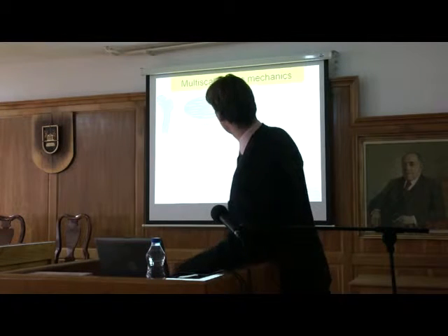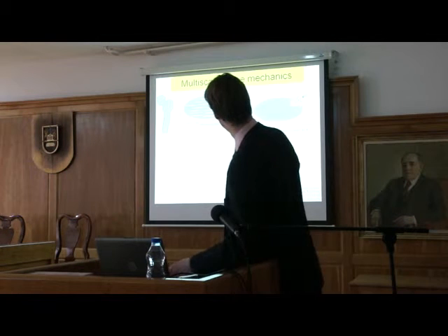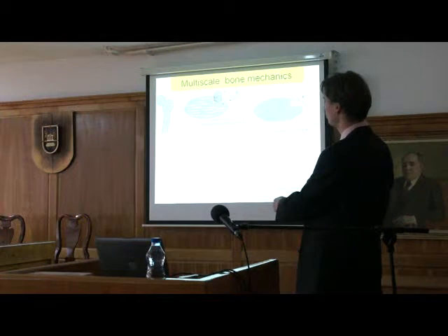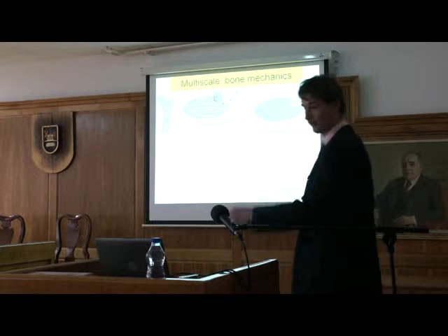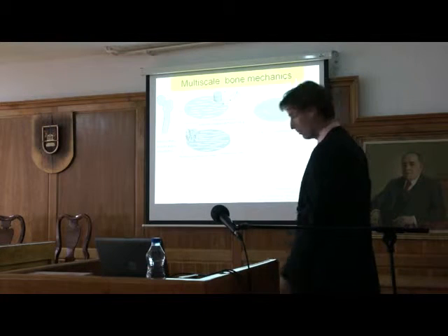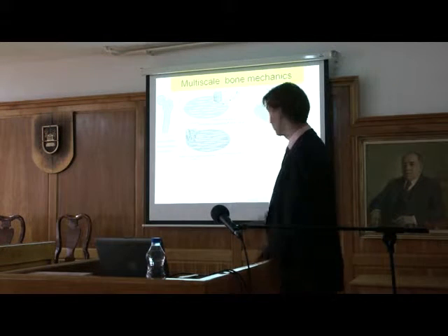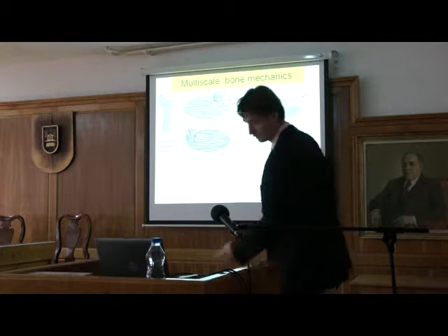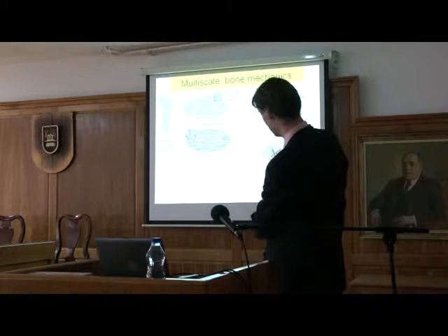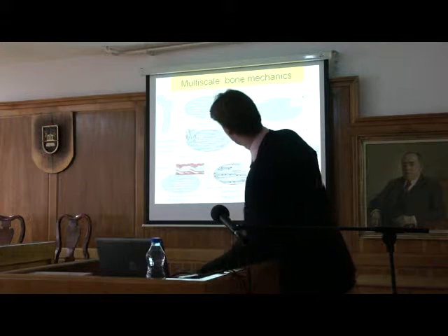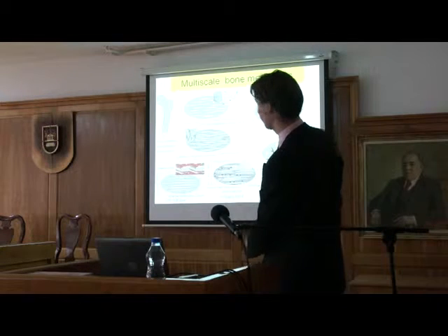And this we apply to our bones, but we have to be a little bit more careful. We need more than one. So this is kind of material at 1 millimeter. Here we would not find constant properties. So we make out of one phase another structure, right? So we again here see the cells swimming, here the lacuna cells, and then here again is our extracellular material. We are back to what I was discussing all the time. How much fibrils are there, how much mineral, how much collagen is all now in here. Is the fibril at the extrafibrillar scale, and then it's here the mineral in the extrafibrillar scale, and finally the fibrils which have some mineral in them, and the collagen itself with another process.